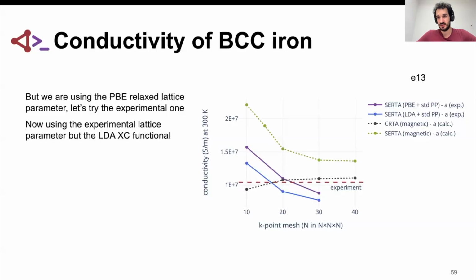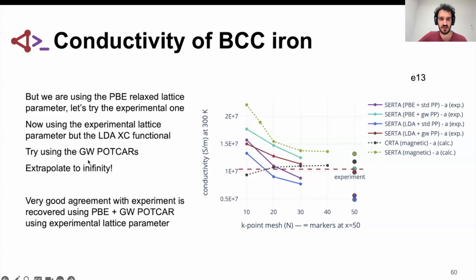We can also try using a different functional, say LDA. So here it's a comparison using the standard pseudo-potential with PBE, the purple line, or with LDA, the blue line. We should extrapolate to infinity, as I mentioned before. And there, what we see is that if we use the GW pseudo-potential, so the teal line and the red line, we are very close to experiment using the experimental lattice parameter. If we use the PBE lattice parameter, then we're not so close to experiment. So this is something to consider when performing these calculations: lattice parameters, pseudo-potentials, exchange correlation.